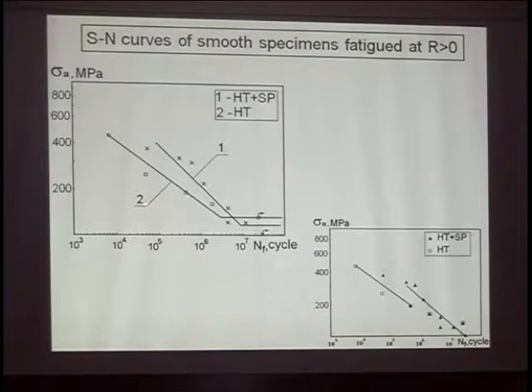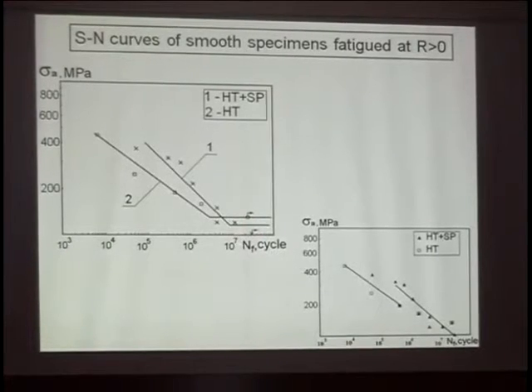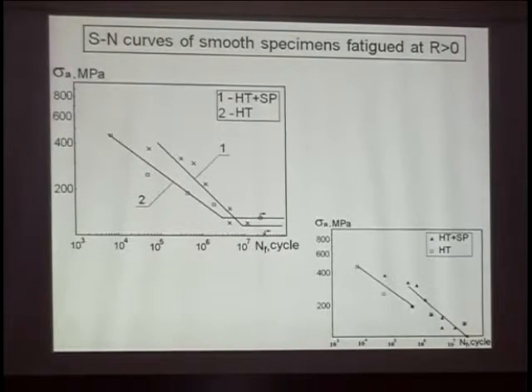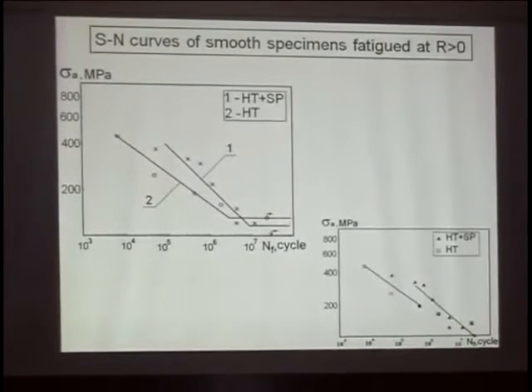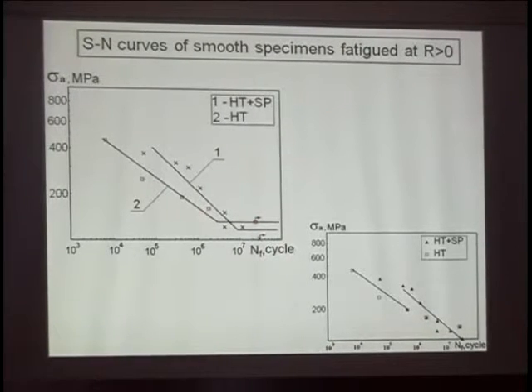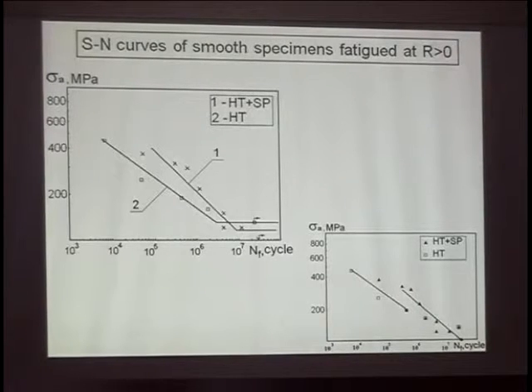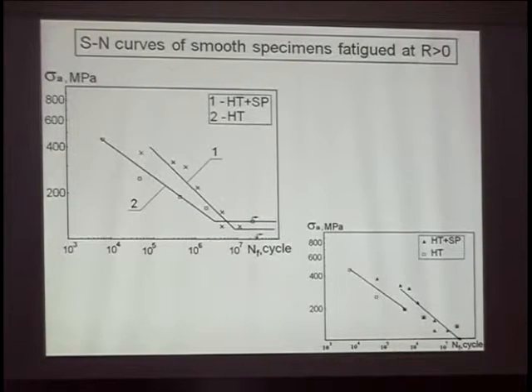If we have only knowledge about the experiment, it's a well-known tradition: we have stress and number of cycles. It's enough. But in this area, we use only knowledge about the number of cycles before failure or not. So we should know if failure will occur in this manner at the surface for a long number of cycles, long time, or not. If we have specimens, we can open them and see if some surface evidence of material cracking exists. I should use this point not for this diagram, only. But it can't really work, because sometimes we open without result. We cannot see. Okay, we can discuss that.